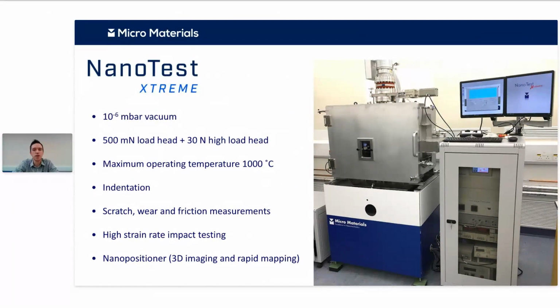Currently, the maximum operating temperature of the system is 1000 degrees Celsius. As we saw in Dr. Raturi's talk, we are heating the sample and the indenter up to a maximum of 1000. But we do have an ongoing development project to extend the range to 1200 degrees Celsius. With this system, we can perform indentation, that's instrumented depth sensing indentation, all the way up to 30 newtons. We can perform scratch, wear, and friction measurements, and also high strain rate impact tests. And we can do all of those things in this high temperature, high vacuum environment.